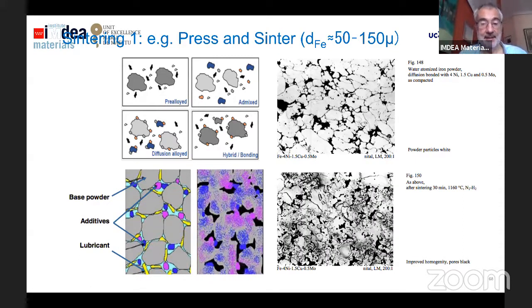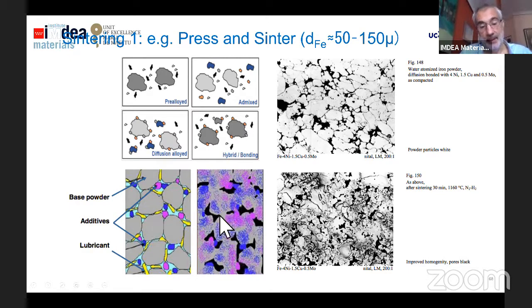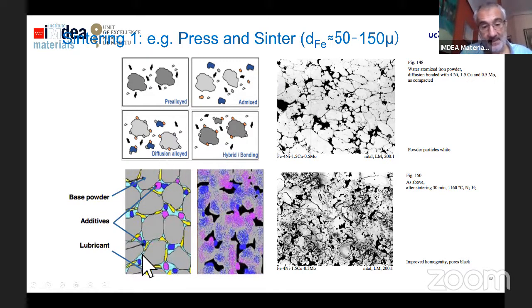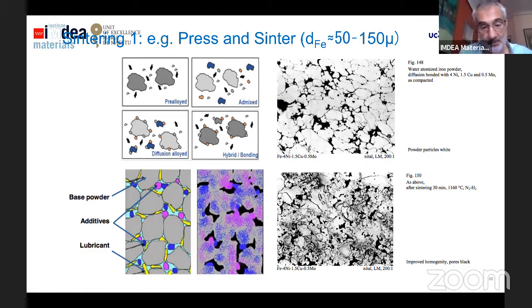Sintering is the next step. The sintering process depends a lot on the kind of powder used, the green state of the part, and the pressing process. After pressing, you have a porous material, and after sintering, you reduce a lot the amount of porosity. Here is an example for a steel — you have the iron powders and the alloying element powders, and after sintering, you promote the diffusion of the alloying elements through the iron-based powder. With this method, you can never reach full density.